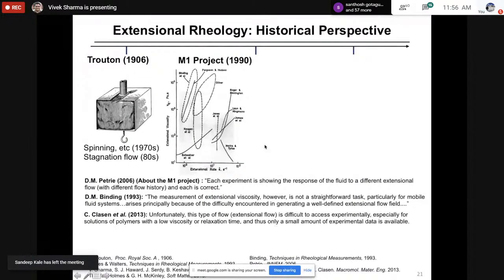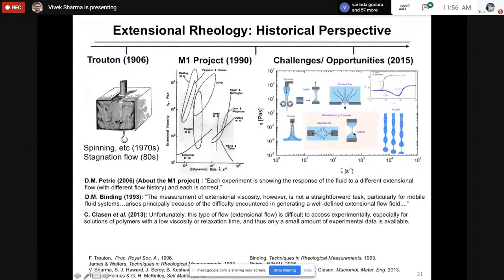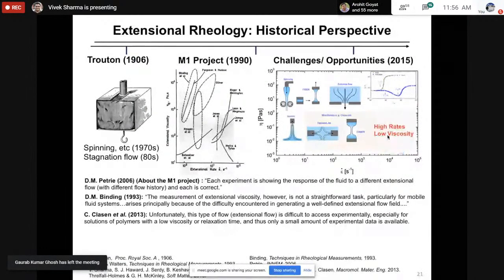In fact, in 2015, I summarized all the different techniques that can be used for a given extensional viscosity, and here's a map of those different techniques. And when I was a postdoc at MIT, we tried to develop a jetting-based rheometer to get to these high rates and low viscosity fluids. As it turns out, when you have viscosity within 10 times water viscosity, it's easy to image this jet as it issues away from the nozzle. But if you increase viscosity or viscoelasticity, the jet flies to such long distances that the experiment becomes hard to control.